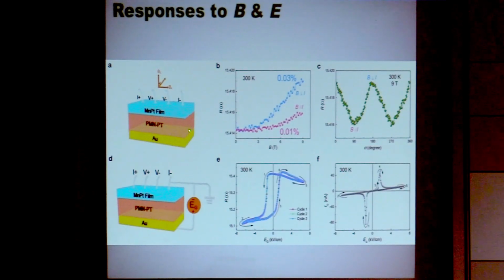For this antiferromagnetic thin film, manganese platinum actually has a very high Néel temperature, around 975 K. That indicates the antiferromagnetic exchange coupling energy of this material is very high. So when we apply a magnetic field of 9 Tesla to this thin film, we get just a negligible magnetic resistance, around